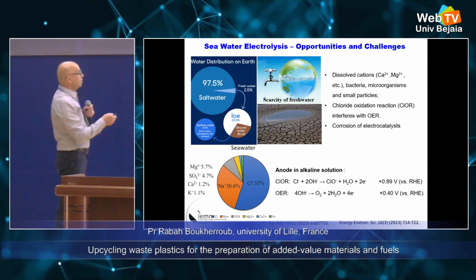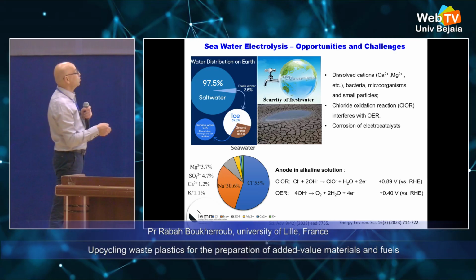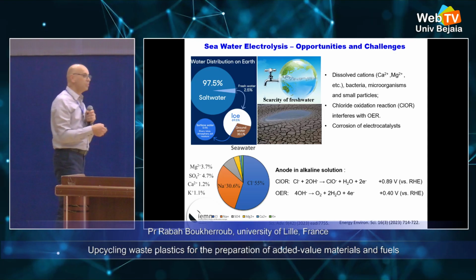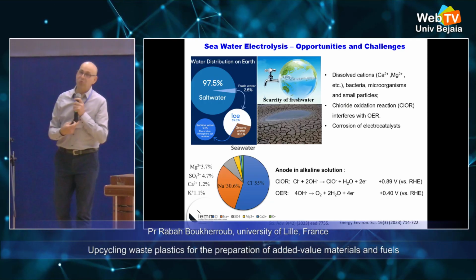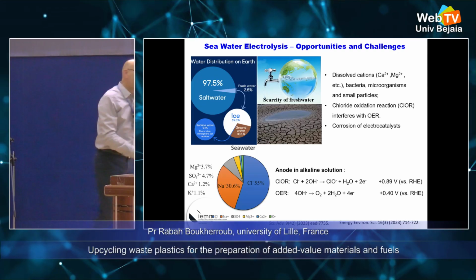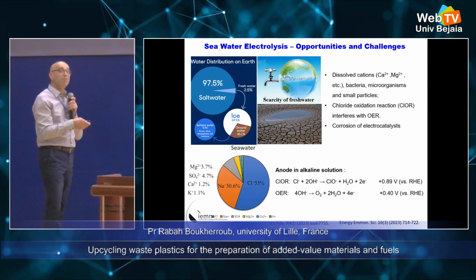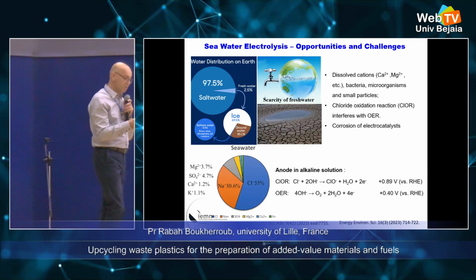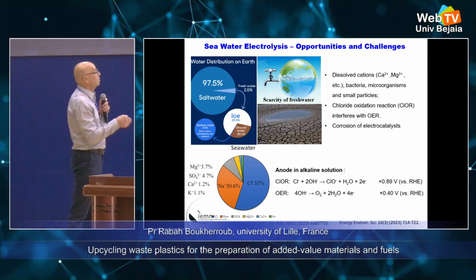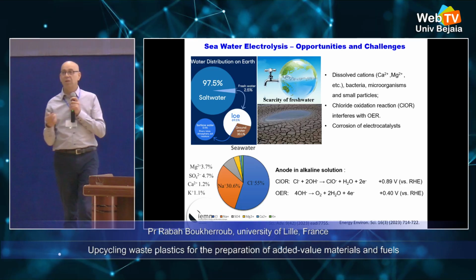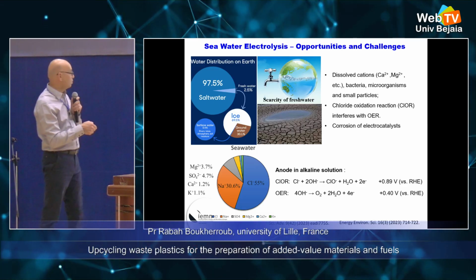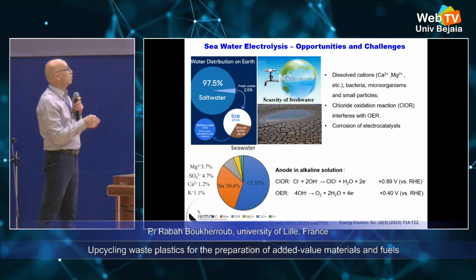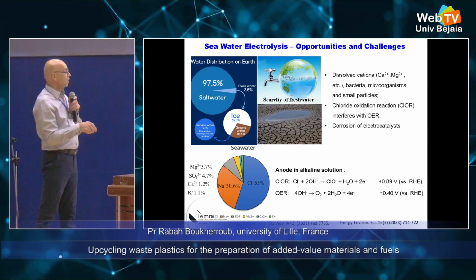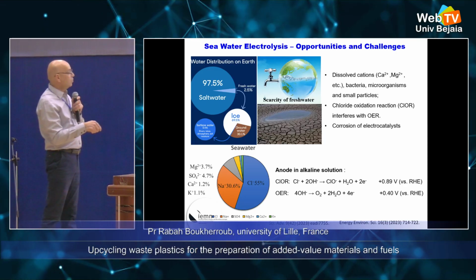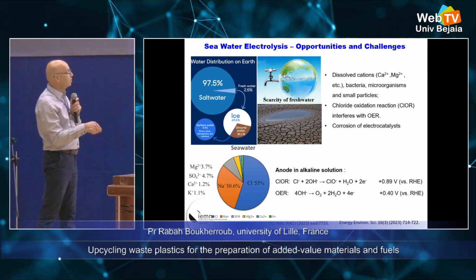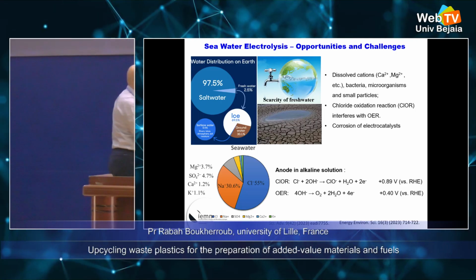And on top of that, we want to work, instead of using fresh water, especially for countries like Algeria, if you want to generate hydrogen at a larger industrial scale, you don't want to use the water you drink, because we don't have enough already for us and for agriculture, irrigation. The ideal is to work with seawater. And seawater, actually, we have a lot over the world, about 97.5%. But it's very challenging to work with seawater because, in terms of the alkaline anode, you have a competitive reaction, but also you have corrosion of the electrocatalyst.